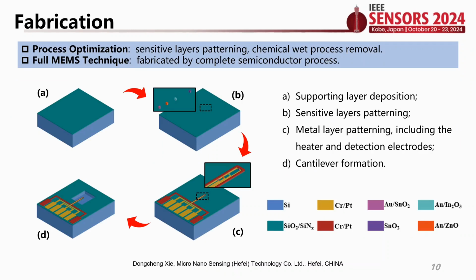The manufacture of the sensor cell is based on typical semiconductor processes. The low-stress supporting layer was fabricated by thermal oxidation and LPCVD. In the traditional process, the sensitive layer is added after the whole micro hotplate was fabricated. However, in this work, we firstly patterned 4 kinds of metal oxides as the sensitive layers through 4 times of lithography and lift-off process. After that, we patterned the metal layer, including the heater and the detection electrodes, at the same time. In the end, the cantilever structure was released through a dry etching method.